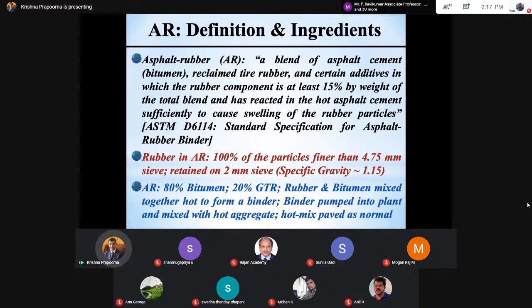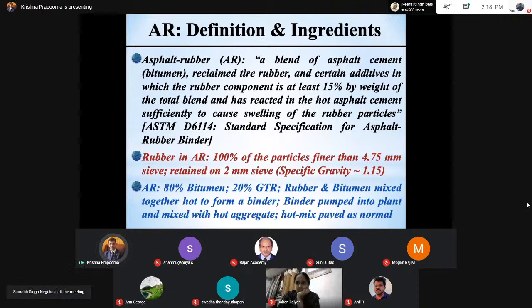Now, that is the same story here. So you are having rubber inclusions in the asphalt mixture blend, which calls for additional space. And if you are not providing additional space, there are two problems. One, drain down, the other is bleeding. So that's how you have rutting and shoving and many other problems. Cracking also can take place, and then finally potholes, right? All of these problems come because people have used CRMB with dense graded.